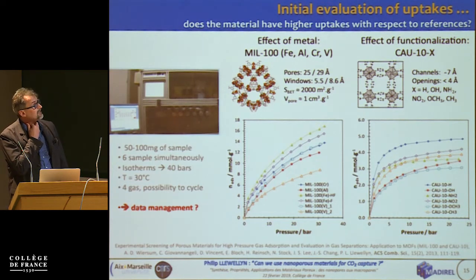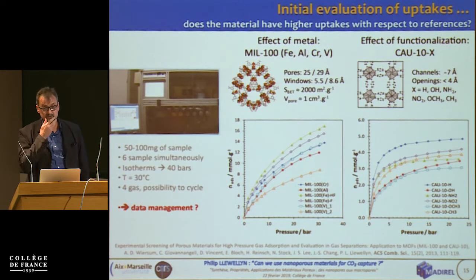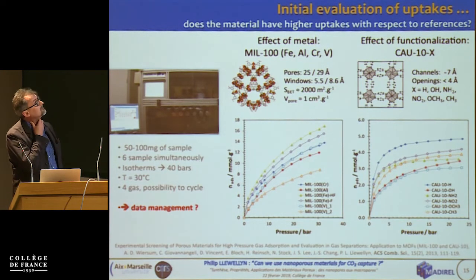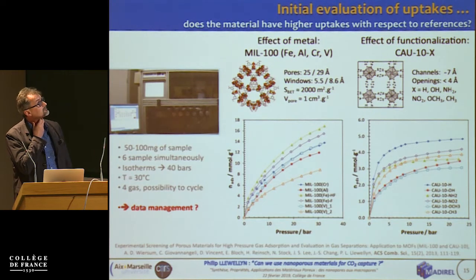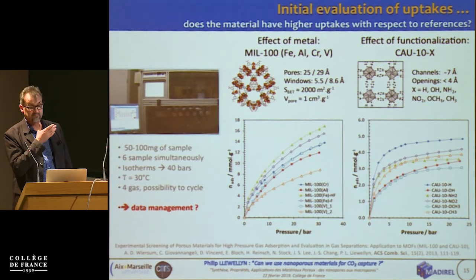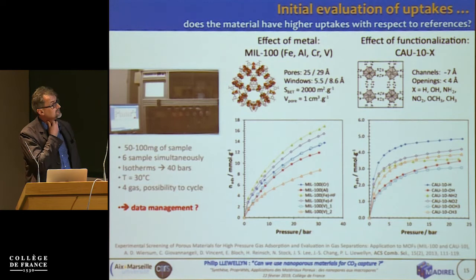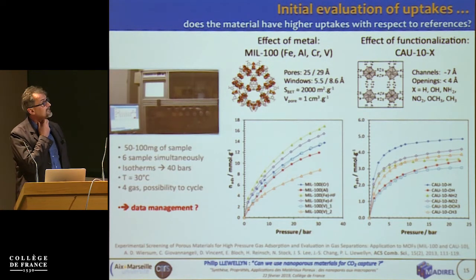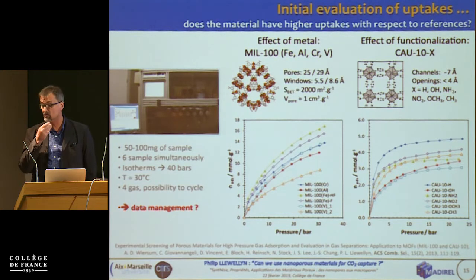So on the right-hand side, you have 2 different series of isotherms with different metal organic frameworks. So Christian's MIL 100, made with different metals, and you can see the different materials we had have different uptakes. And we can see for the vanadium sample, we had 2 different samples, one which is maybe of a little bit lower quality than the other. So it's a good way to screen through materials.